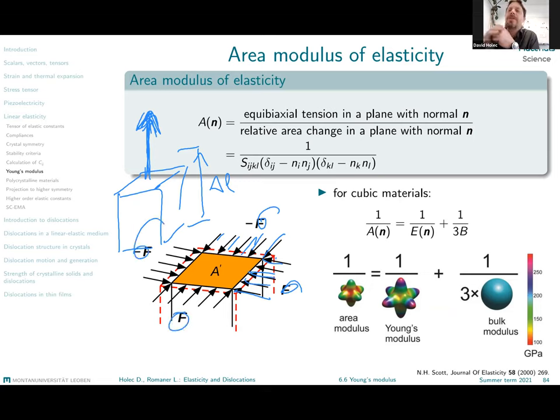Here we have in all of these directions the same stress. What we measure is the change of the cross-section area perpendicular to the direction to which all these biaxial stresses are perpendicular. And this relationship between the applied biaxial stress and resulting change of the area is then described by the area modulus of elasticity. Obviously, it is again a quantity which would be directionally dependent. Now, N describes the normal to the plane at which we act with this biaxial stress and where we measure the change of the area.